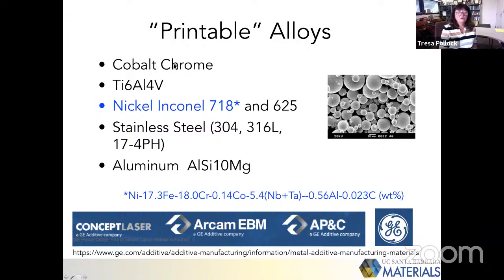So there's cobalt chrome, and this is the alloy that GE has used to make their fuel injectors that are currently in service. One can get titanium, a couple nickel alloys, stainless steel, and aluminum casting alloys. But in fact, the selection is rather limited. And so one of the challenges is to develop alloys that are tailored to this process.